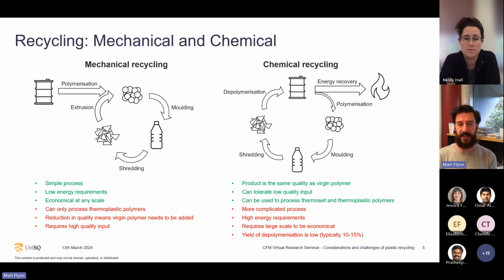The downsides of this is that it's more complicated. It needs a much larger scale to operate efficiently and especially to be economical. Because there's extra steps, it's got higher energy inputs, and also the process itself is a higher energy input. It also typically gets very low yields, so usually 10 to 15% with current technology. So the best approach is really a mix of these, mechanically recycling what we can, chemically recycling what we can't, and then recovering energy from all the rest.